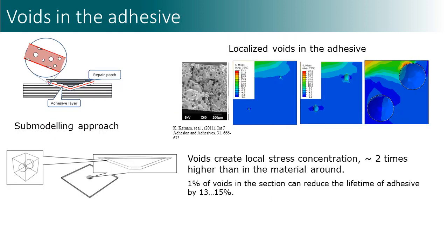In order to analyze the effect of voids, we used submodeling techniques. It means that a small element is placed in the adhesive and assigned various structures. In this way, the effect of the structure of the adhesive on the stress field is studied. As expected, the voids in the adhesive create a drastic local increase of stresses. Thus, we can say that voids in the adhesives, especially in the upper part, should be prevented.